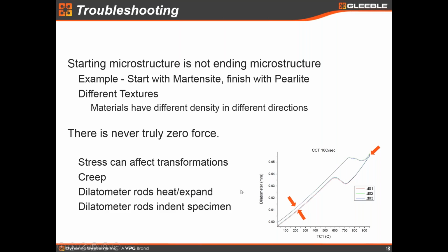The dilatometer itself is cooled, so we get very few temperature effects there, but the quartz that we choose for those dilatometer rods is obviously very low thermal expansion. That's one of the reasons that quartz is used for these applications, but that does have a little bit of thermal expansion. And so a little bit of expansion of those rods can give you a little bit of this failure to close on some of these loops.